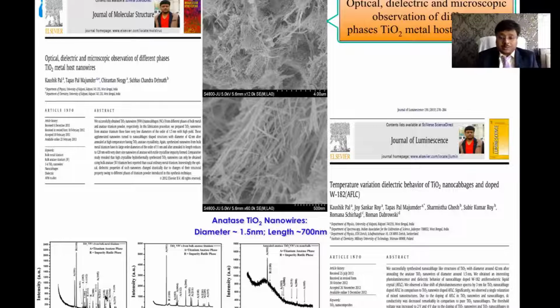So the same procedure, hydrothermal process. You can see the rutile peak is already gone after annealing, so ultimately we get only the anatase. It is confirmed by FESEM: 1.5 nanometers diameter, very ultra-thin nanowires, and 700 nm length of the nanowires we observed. So it's a very novel work, and we can apply it for doping with a ferroelectric liquid crystal for nano cabbages. With the nano cabbages, I will show you.